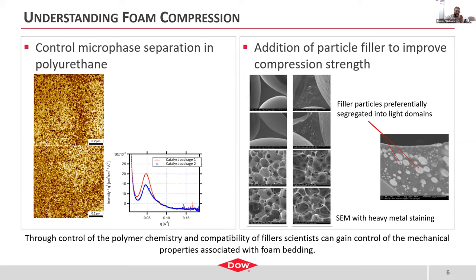However, when the isocyanate reacts with either the hydroxyl group of the polyol or water that is often in the formulation, it'll form polyurea and urethane linkages. And those often have a much higher mechanical strength. Those what are called hard domains are not miscible with the polyether or polyester polyol domains. So you end up with a microphase separation, and controlling this microphase separation can control things like how fast your foam cures. It can control things like how hard the final foam is, and things of that nature. And we can use different catalysts,